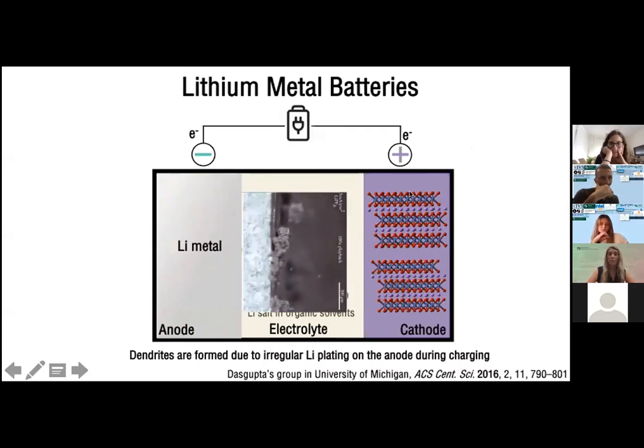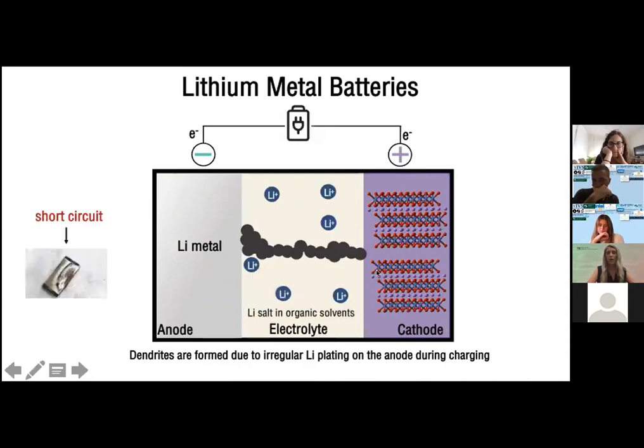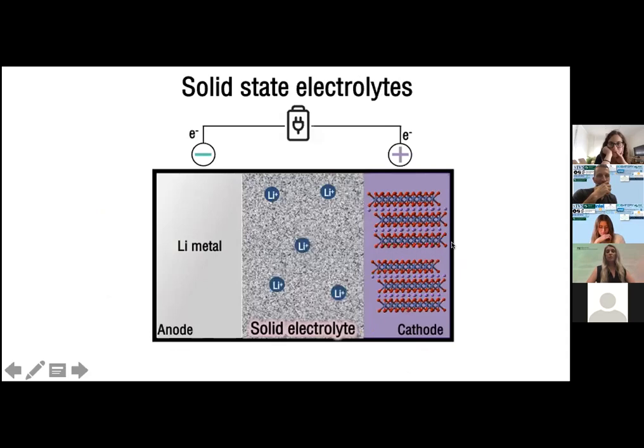During charging, lithium can deposit irregularly on the anode side, forming spiky structures, as you can see here, which are called dendrites. And they continue growing, and may reach the other electrode and cause a short circuit. And of course, in the presence of flammable liquid electrolyte, your cell can explode, and you don't want your vehicle to explode. So in recent years, there have been a lot of efforts to fix that.